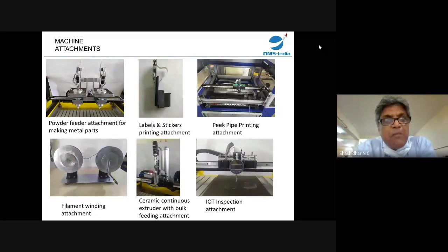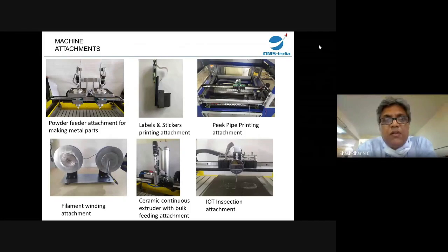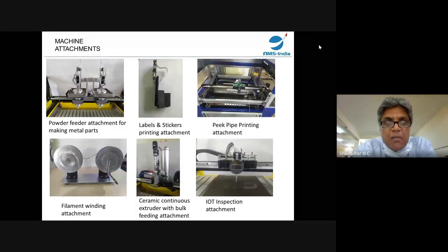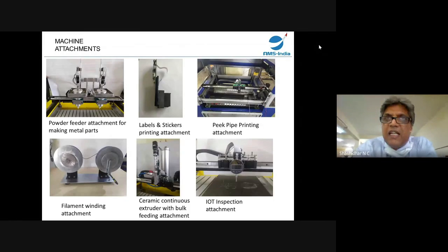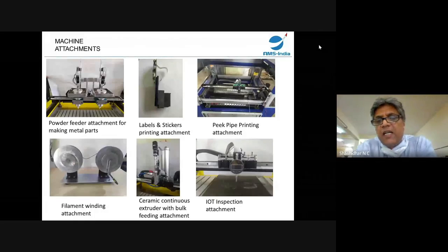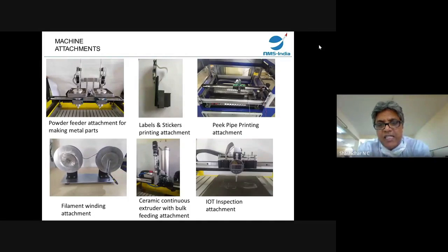There is an attachment for printing PEEK pipes. We are working with Vikram Sarabhai Space Center in Trivandrum. There is a new methodology by which they want to make the fuel transportation pipes in the rockets, which can go down to minus 130 degrees centigrade. So we are printing PEEK and carbon fiber mix in this particular circular condition, and then they are testing it out to take up to 40 bars pressure and minus 135 degrees centigrade to see whether it leaks or how it works. If this is successful by the VSSC, then they will be able to make rockets which can take a higher amount of load, or more number of satellites can be launched.